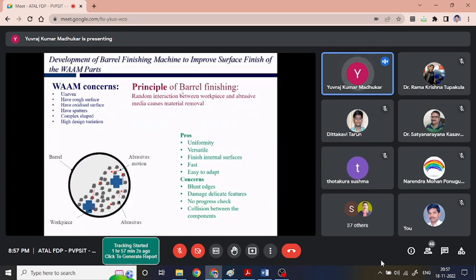But again, in the case of WAAM, post-processing remains a matter of concern. Despite monitoring and control, and achieving good success with it, since the bead melt pool size is bigger, the deposition accuracy is certainly relatively poor compared to any powder-based, laser-based process. So to minimize post-processing, we can come back to our first slide where I showed that we can machine it, depending on the application.